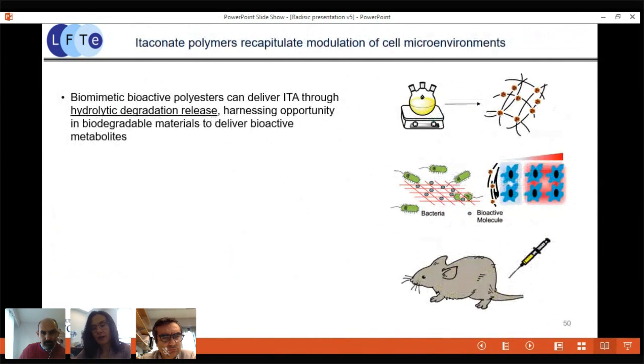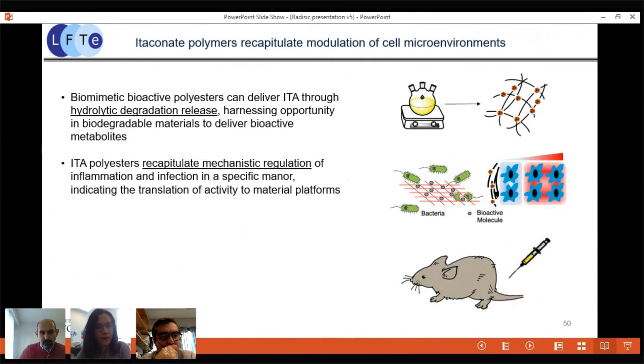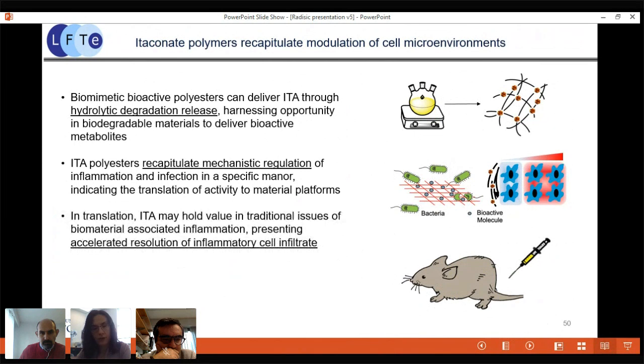So through this itaconate work, we saw that biomimetic bioactive polyesters can deliver ITA through hydrolytic degradation release. And this really harnesses the opportunity of these biodegradable materials to deliver immunomodulatory molecules. And we saw through a number of tests that are focused on confirmation of what is known about the effect of ITA in the body, that we can regulate both inflammation and infection in a very specific manner that is consistent with the ITA mechanism. And so in translation, that may hold value in constructing new biomaterial scaffolds from these polyesters that will enable us to accelerate resolution of inflammatory cell infiltrate and to some extent prevent implant infection.